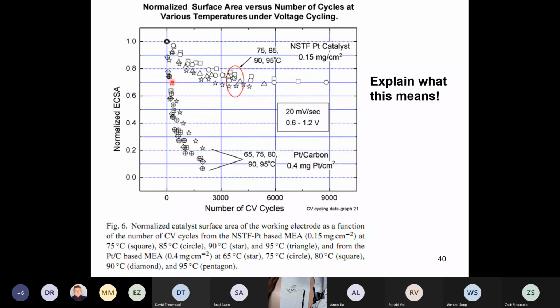So let's take a look at this here. This is an example that 3M put out showing the advantages of their support over the platinum on carbon. What's happening here is the cells were doing CV cycles, I think between 0 and 1.1 volts. And while that's happening, the carbon support is degrading, and you're measuring the electrochemical surface area normalized to the beginning of the test. So the platinum supported on carbon had the burn off of the carbon and poor performance after a while. Whereas on the nanostructured thin film support, there was nothing to oxidize away. The organic material was perfectly stable, and there's so much platinum whiskerettes there that they contact one another. You don't rely on the carbon black to make the contact.